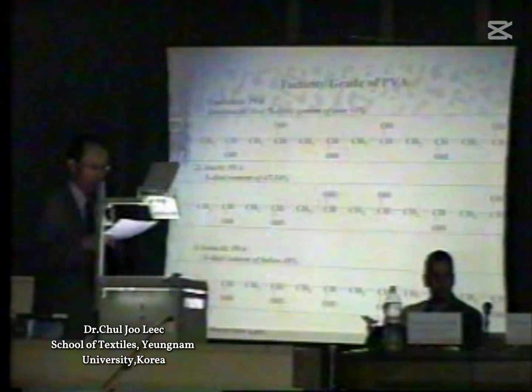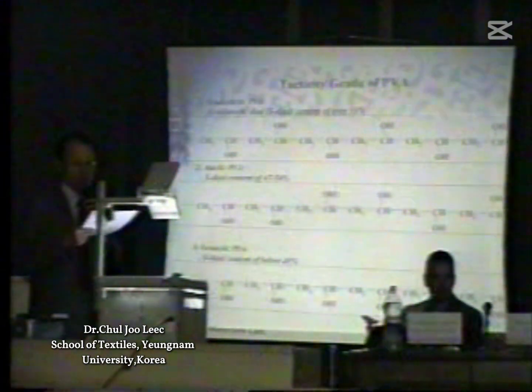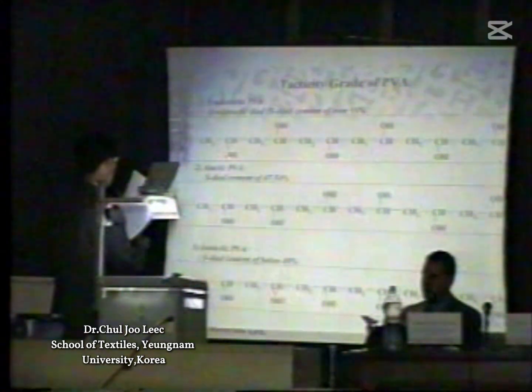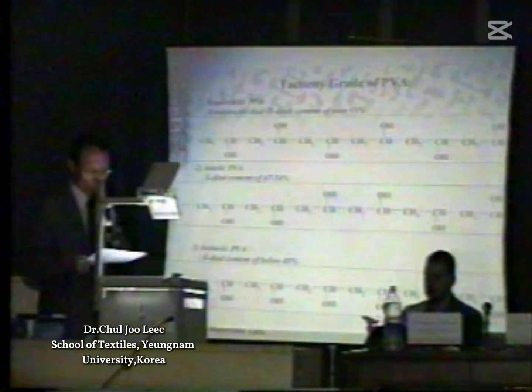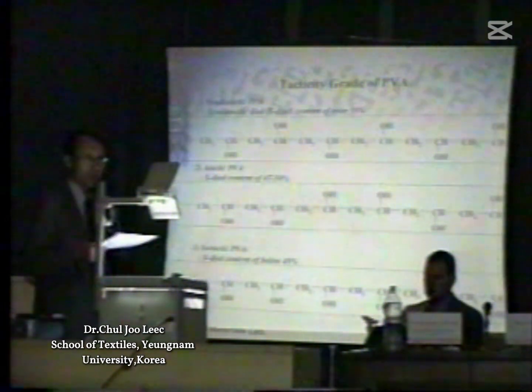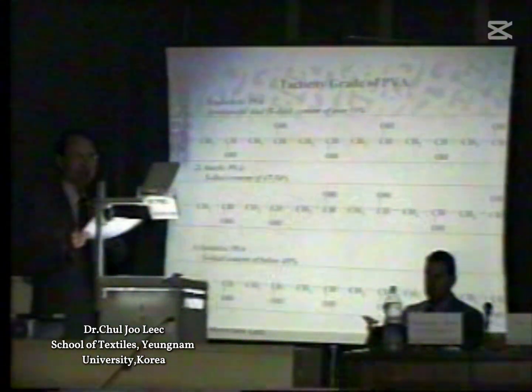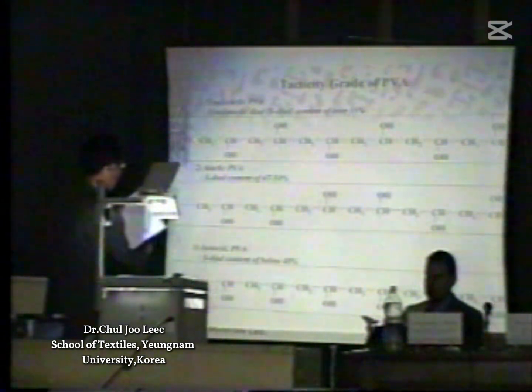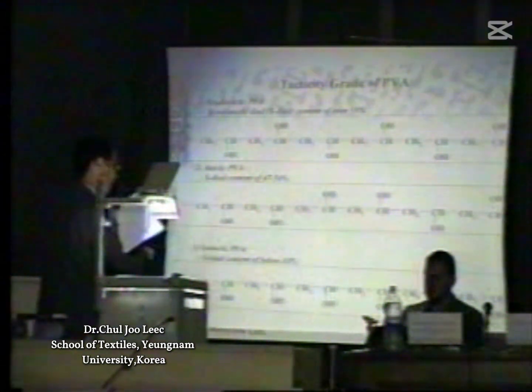It is well known that the stereoregularity of vinyl polymers can change the physical and mechanical properties. Vinyl polymers are classified into three tacticities, such as isotactic, atactic, and syndiotactic ones. This figure shows the syndiotactic stereoregularity, and this chain shows the atactic polyvinyl alcohol, and finally, the isotactic PVA is like this. In the case of PVA, syndiotactic diad means two syndiotactic monomeric units, and over 55% is usually called syndiotactic. This slide shows syndiotactic means that from the plane of the main chain, one pendant group is upside and the other pendant group is downside of the plane of the chains.